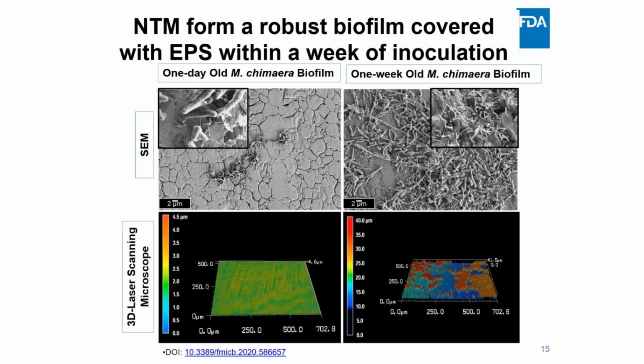So I want you to know that M. chimaera are slow growing species. So it would take about 14 days to even see a colony. So we were surprised to see that within 1 day of inoculation, we can see these M. chimaera cells are attached to stainless steel. And then after a week, on the right image over here, after just 1 week, a dense mature biofilm has formed, clearly covered by an extra polymeric-like substance. So this image provides critical visual evidence that even slow-growing NTM species like Mycobacterium chimaera can quickly establish into robust biofilms on medical device surfaces, reinforcing the urgent need for better prevention and cleaning strategies in reusable medical devices.